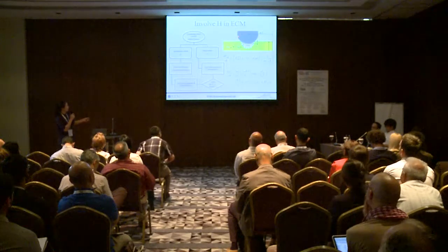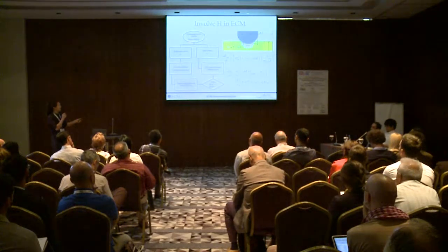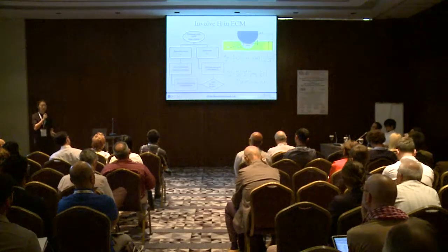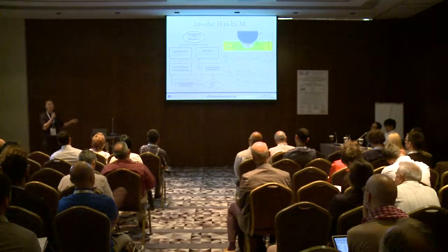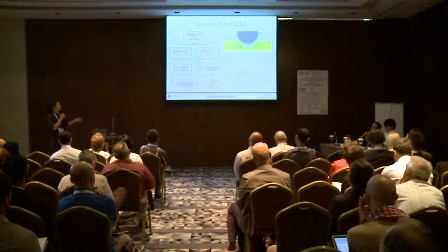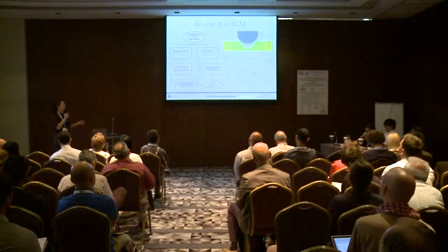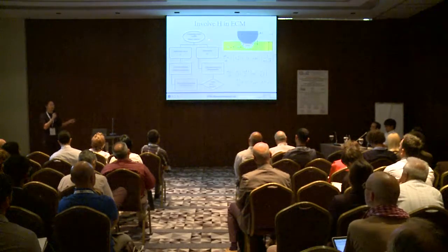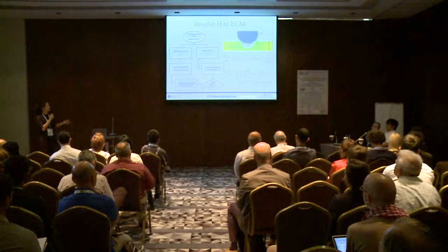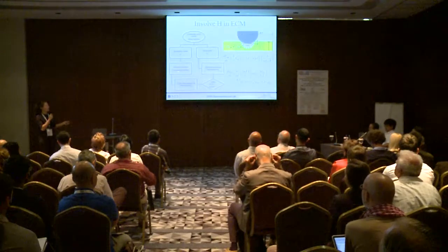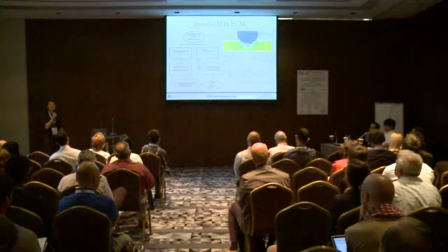We have the expanding cavity model for the indentation, and the stress can be decomposed into two components. The shear component determines dislocation nucleation and motion, and that will finally contribute to the indentation force and displacement evolution. The second component is the hydrostatic stress. We use the process in which the chemical potential drives hydrogen diffusion, in the same manner as Professor Song and Curtin's work.